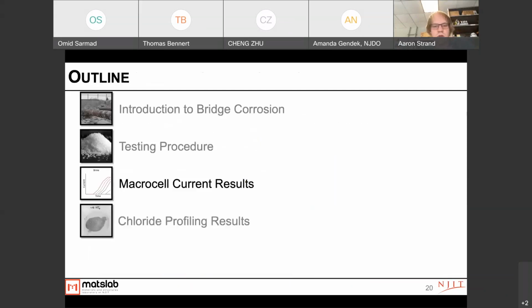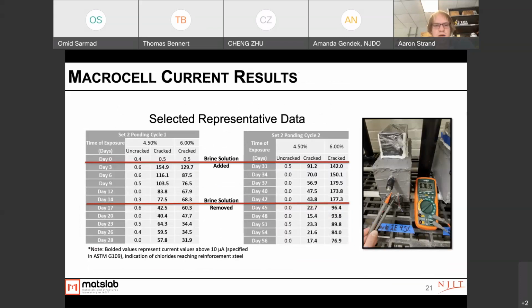So moving into the macrocell current results, this is what the data looks like when it was collected. We can see that for the 4.5 and the 6% crack specimens, even on day 3, we were getting values that were above the threshold value, and those are all bolded. And in the uncracked specimen, the values in essence represented any background values within the multimeter device that we were using.